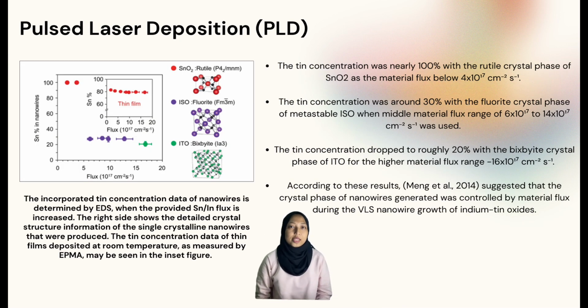Next, the figure explained that the tin concentration was nearly 100% with the rutile crystal phase of stannic dioxide as the material flux below 4 times 10 to the power 17 cm-2 seconds-1. However, the tin concentration was around 30% with the fluorite crystal phase of metastable ITO when middle material flux range of 6 to 14 times 10 to the power 17 cm-2 seconds-1 was used. The tin concentration dropped to roughly 20% with the bixbyite crystal phase of ITO for the higher material flux range. Meng et al. 2014 suggested that the crystal phase of nanowires generated was controlled by material flux during the vapor-liquid-solid nanowire growth of indium tin oxide.